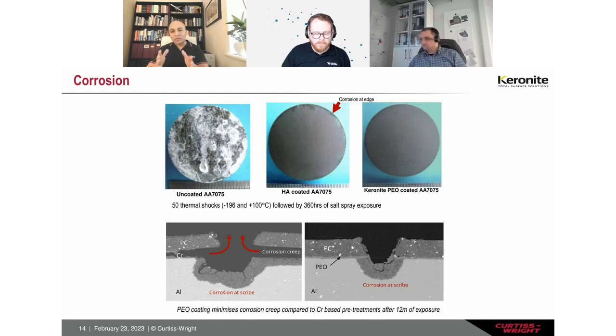So what is effectively happening is on the damaged zone, you are expecting the corrosion to happen as normally you'd expect. It corrodes, but A, it is not driven badly by the galvanic interactions because there is no other cathodic couples. And B, the corrosion is not pushing downwards. It is just stopping there. Because the ceramic layer is stopping further propagation, the corrosion creep. You don't have that in other phosphate treatments, because usually you tend to push those corrosion products underneath. And because the bond is not very strong, it tends to migrate underneath and gradually pushes up those polymeric layers, resulting in blisters and further propagation and peeling off of the polymer layer. So that's exactly what is happening there.